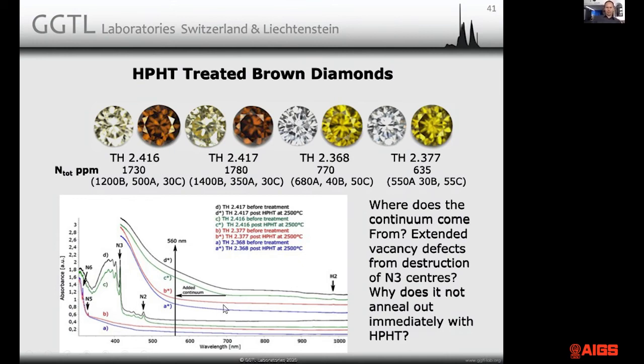Post irradiation, post HPHT treatment, you only have a continuum absorption. In consequence, A star and B star correlate to perfectly yellow diamonds. So these ones were transformed by HPHT treatment from perfectly colorless into canary yellow. So they were as yellow as a canary yellow diamond. In contrast to this, the stones very rich in N2 and N3 center, N2 being part of the N3 center obviously, were transformed into brown. They were just slightly orangey brown, dark orangey brown after the HPHT treatment.